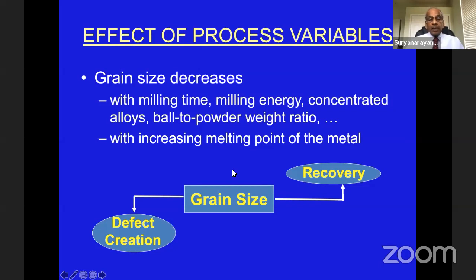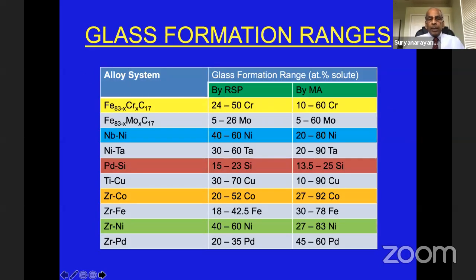The balance between the defect creation and the recovery will determine what the final grain size is. To put it very succinctly, the grain size decreases with increasing milling time, with increasing milling energy, with increasing solute concentration, high ball to powder weight ratio, and with increasing melting point of the metal. So you can determine what are the more important factors for your investigation. Metallic glasses also are formed by these techniques, both RSP and MA. Just like in the solid solution cases, here also by mechanical alloying, you're able to increase the glass forming composition ranges. They are more than what is possible by rapid solidification processes. It is a very similar technique. Essentially, the MA seems to be more effective.